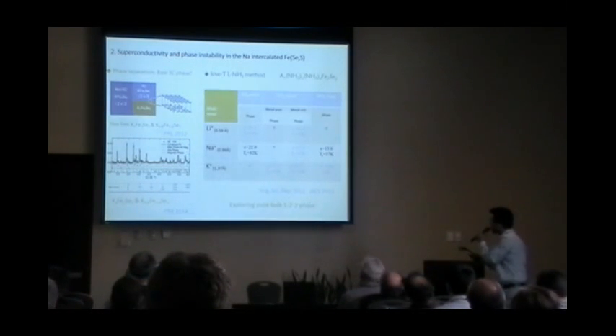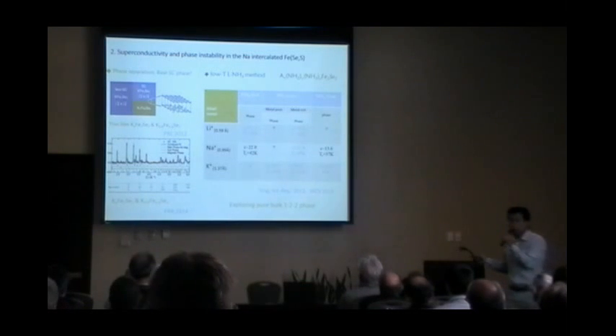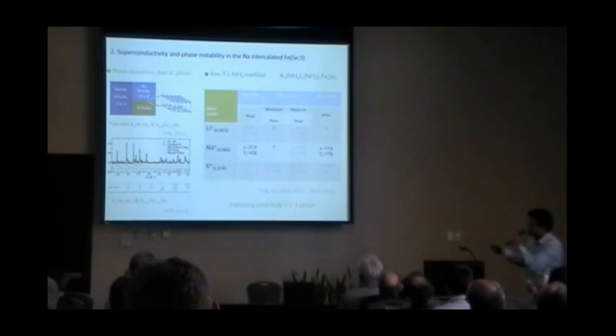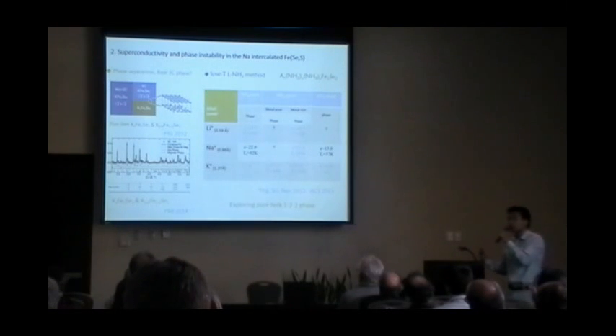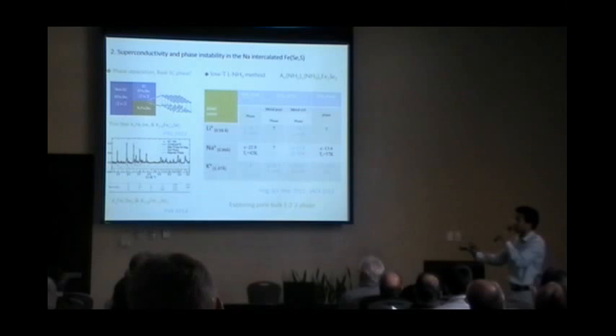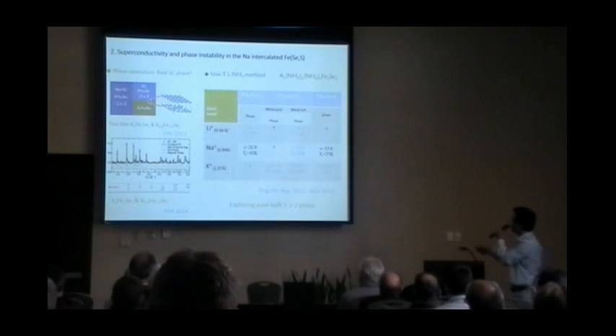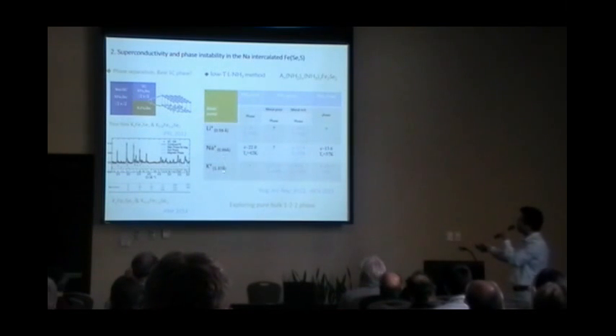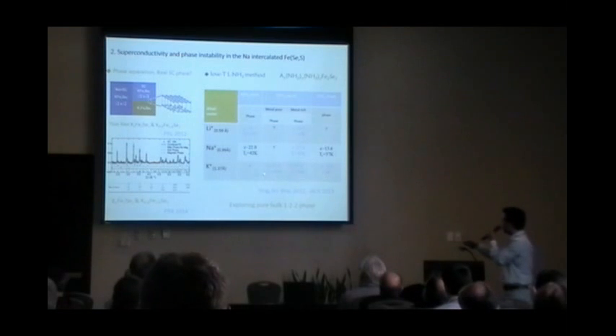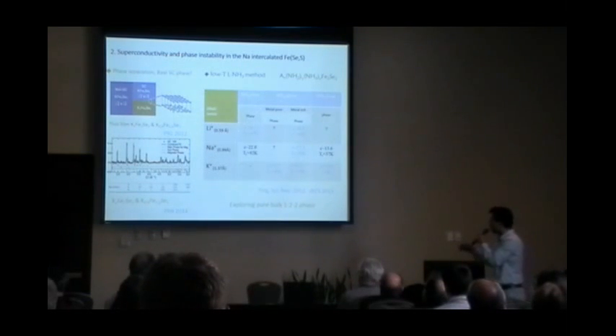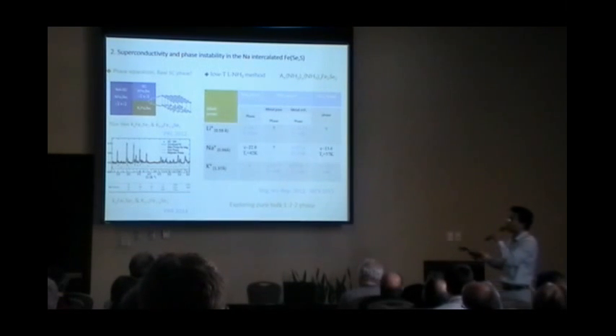So in 2012, there is a new report. They use some kind of chemical method. They use a low temperature ammonia method for intercalation, and they choose lithium, sodium and potassium. They got a lot of the superconducting phase shown in the blue one. So up to 2012, there is still no very clear clue about which one